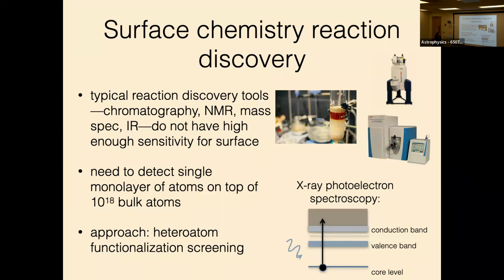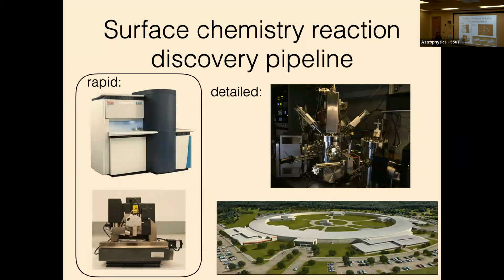So basically, one of the real challenges here is that we now need to be able to do reaction discovery, but on this single monolayer of atoms at the diamond surface. And the typical reaction discovery tools are things like chromatography, liquid phase NMR, mass fragmentation mass spec, infrared absorption, and none of these things have sufficient sensitivity to look at one monolayer of atoms on top of an Avogadro's number of other atoms. So our approach instead was to intentionally functionalize with heteroatoms and then use X-ray photoelectron spectroscopy to screen. The idea here is that you can do a lot with this screening, with these rapid feedback tools in the lab, and then you can back it up with more detailed measurements using detailed surface spectroscopy and going to a synchrotron to look at X-ray absorption.